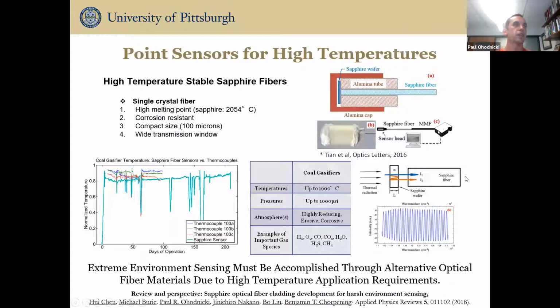They can calculate temperature. And this is an example of applying that sensor in a gasifier at temperatures which can be as high as 1600 degrees Celsius, where it was shown that because of the robustness of sapphire fibers and because of the robustness of optical-based sensors, they far surpass the lifetime of a traditional thermocouple in that case.